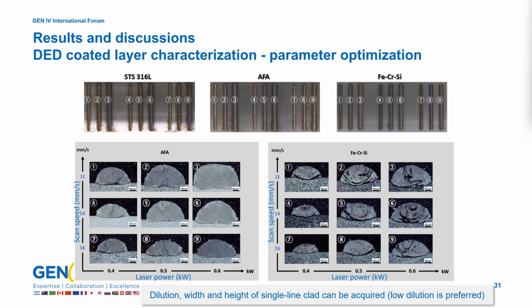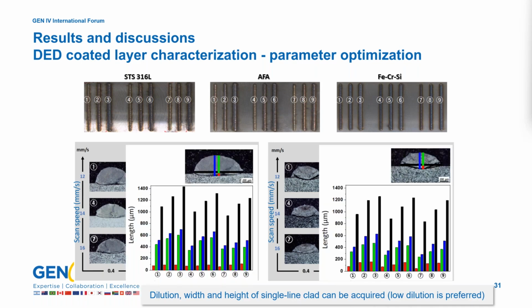However, in the process conditions of specimen 7, because the laser transfer speed is the fastest under the lowest laser power condition, the bonding strength is expected to be weak, so it was excluded from the optimal process conditions. Therefore, regardless of the powder type, the optimal process condition for producing a single line clad is laser power of 0.4 kilowatt and a laser transfer speed of 14 millimeter per second.